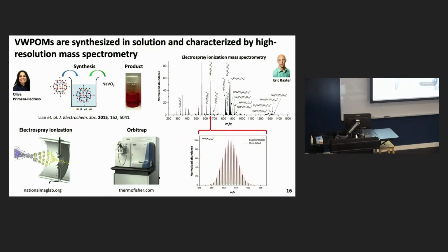So we have a team that worked on this. First, as I said, we had to produce this vanadium-doped cluster, which is done in solution and looks something like this. Once you produce this solution, if you look at it with analytical mass spectrometry, you can see a distribution of things in solution containing various numbers of tungsten and vanadium atoms. If we were to just take a droplet of this, all of this material would be on our surface, and it would be very hard to correlate the activity that we see with any given species.